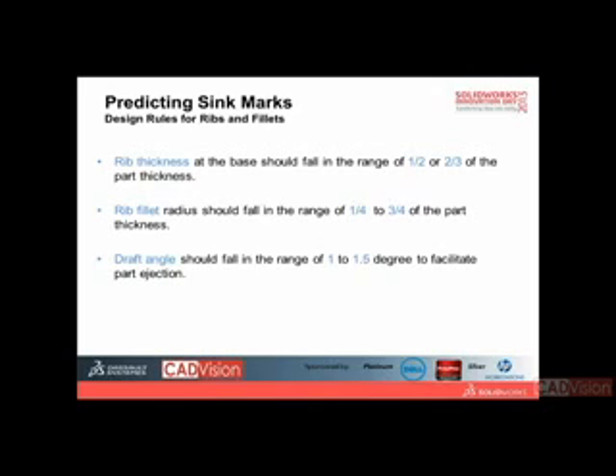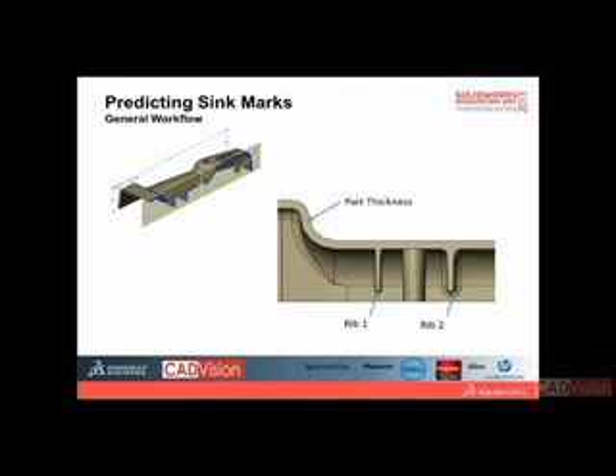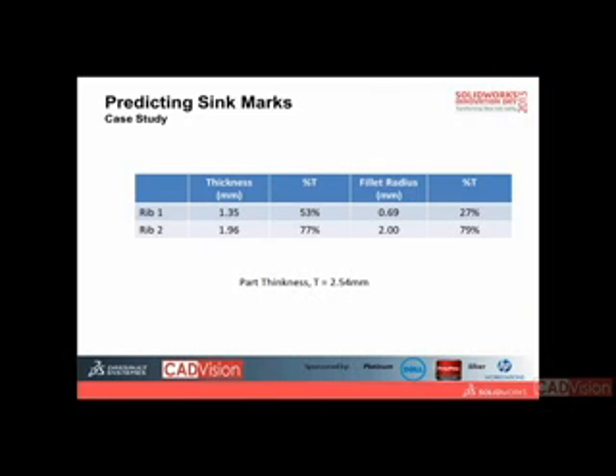Okay. So if you follow the design handbook, they have 3 basic rules regarding avoiding the sink marks. First is the rib thickness has to be between half and two-thirds of the overall thickness. The fillet has to be 25% to 75%. And the draft angle is normally 1 to 1.5 degrees. So if we come back and see, rib 1 and rib 2 have different thickness and different fillet radius. The first one is 1.35, which is 53%. It's inside this design rules-of-thumb safety zone. The fillet radius is also in the safety zone, 25% to 75%, this is 27%.